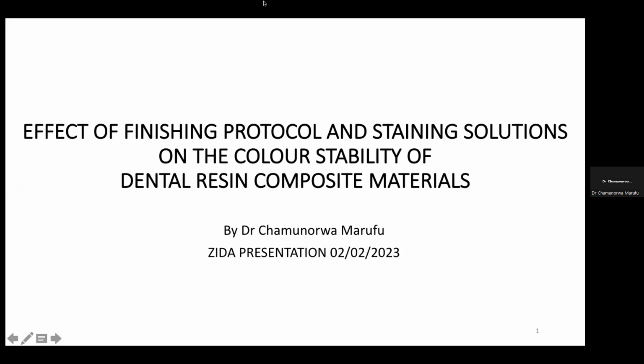Yeah, so the recommendation is, if you are going to be doing composite restorations in the anterior region, it might be best to invest in a good polishing system, and also other aspects of the restorative procedure, which I didn't mention in this presentation because of time. Like, for instance, the curing. In an earlier slide, I mentioned that intrinsic discoloration was due to the manufacturer's formulation, but the operator can also cause that if they don't completely cure the composite. And also remember that the degree of conversion in direct composite is around 50 to 65%. So it would also be wise for dentists doing this type of restoration to invest in a good light curing system. Thank you.